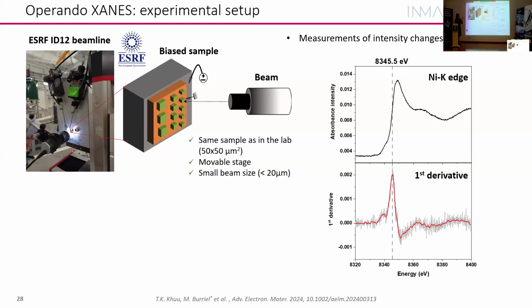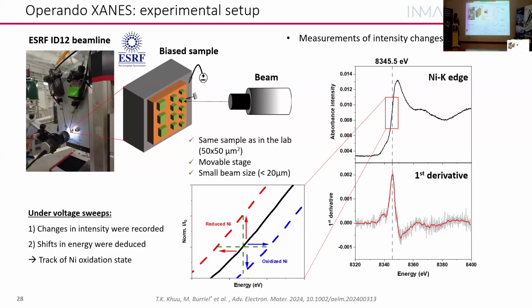So maybe they're 20 minute measurements, and that was not compatible with our operando measurements where things switch fast. So what did we do? First we did the whole measurement, but then we took the first derivative and found the edge point. And then we just looked at this edge point while we were cycling with time.